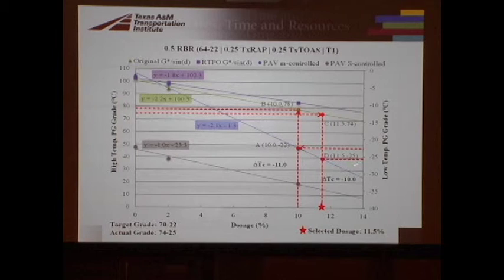And then we just double check. We're at a minus 25, which is still a minus 22 grade. So we get a 74 minus 25 with our new dosage of 11.5%. That meets the target, and it also reduces the delta TC to minus 10.